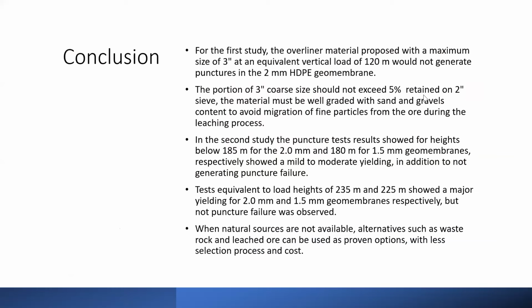And the conclusions for this case were, in the case of the first study, that 120 meters maximum height and 3 inches as a maximum size of the overliner will not generate punctures for that type of geomembrane. But for that, the portion of 3 inch coarse size should not exceed 5% retained on the 2 inch sieve. And the material must be well graded with sand and gravel content to avoid migration of fine particles from the ore during the leaching process.